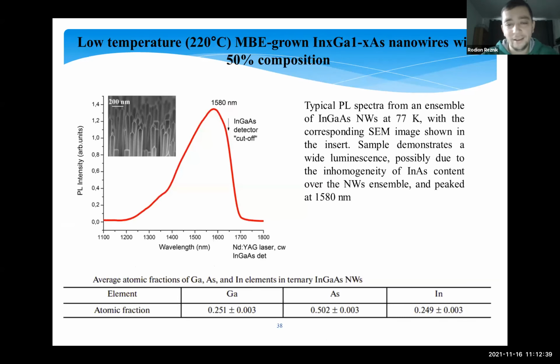And finally, this is my last result, my last slide. Also at low temperature, even 220 degrees, we have grown indium gallium arsenide nanowires on silicon with a 50% composition of indium or gallium. Like George Zilin said in his talk for indium gallium nitride about the miscibility gap, the same story applies to indium gallium arsenide nanowires. It's not so easy to achieve 50% indium content in this solid solution, but with growth of nanowires, we can achieve this content.